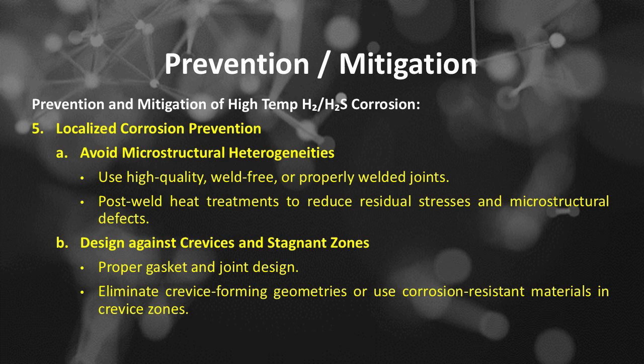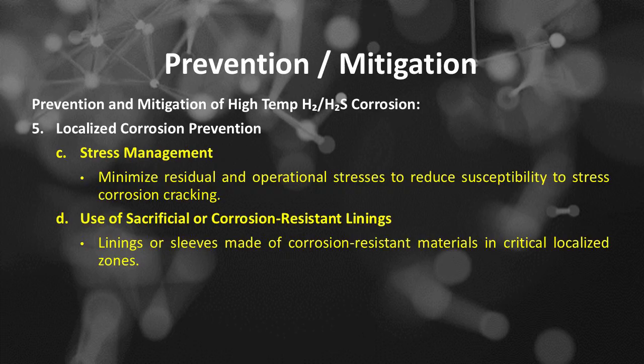Number 5 of prevention and mitigation methods is localized corrosion prevention. A: avoid microstructural heterogeneities. Use high-quality, weld-free, or properly welded joints, post-weld heat treatments to reduce residual stresses and microstructural defects. Number B, design against crevices and stagnant zones, proper gasket and joint design. Eliminate crevice-forming geometries or use corrosion-resistant materials in crevice zones. Localized corrosion prevention and mitigation. Number C, stress management. Minimize residual and operational stresses to reduce susceptibility to stress corrosion cracking. Number D, use of sacrificial or corrosion-resistant linings. Linings or sleeves made of corrosion-resistant materials in critical localized zones.